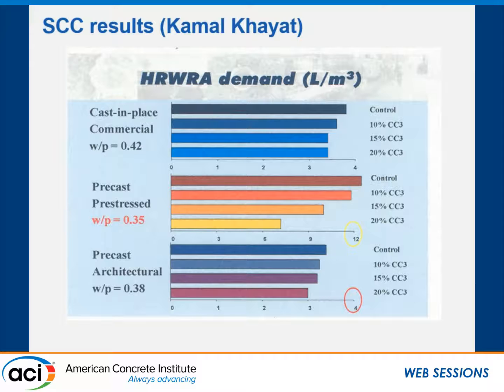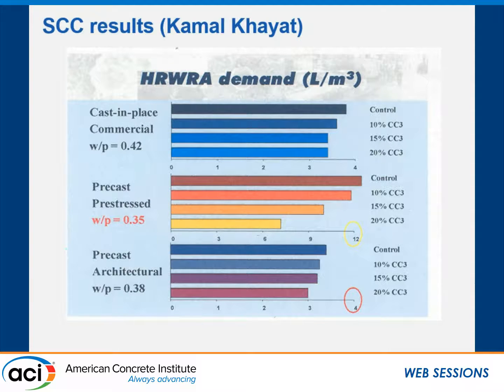Yesterday Kamal presented SCC data that I want to revisit. In every one of these mixes — cast-in-place SCC, pre-stressed using Type 3 cement, pre-cast pre-stressed, and pre-cast architectural — he used 10%, 15%, or 20% replacement with a 3-micron D50 limestone filler. Every time he reduced the demand for high-range water reducer.